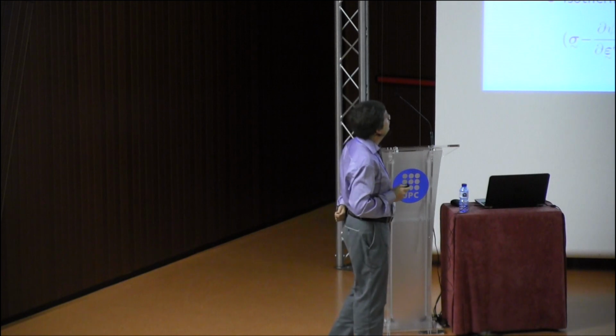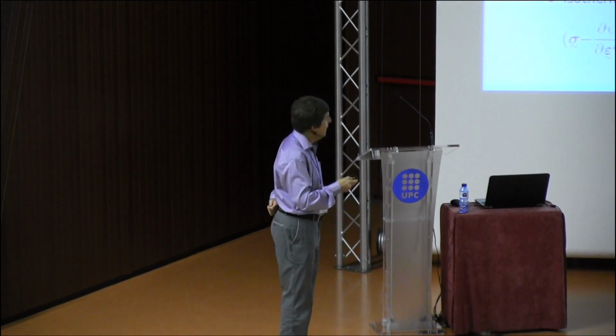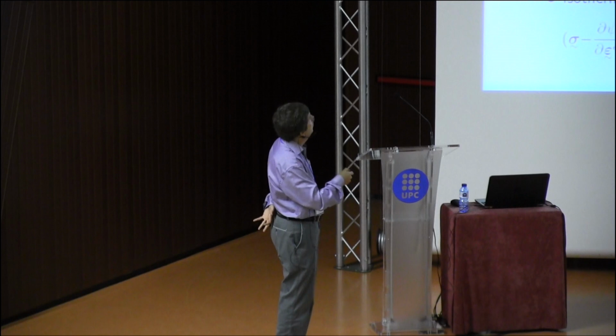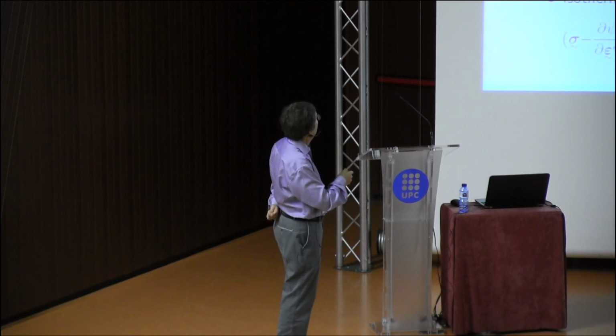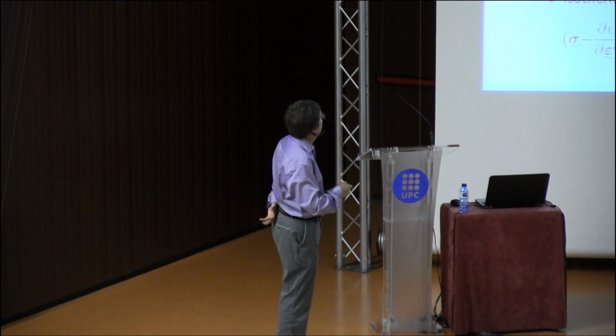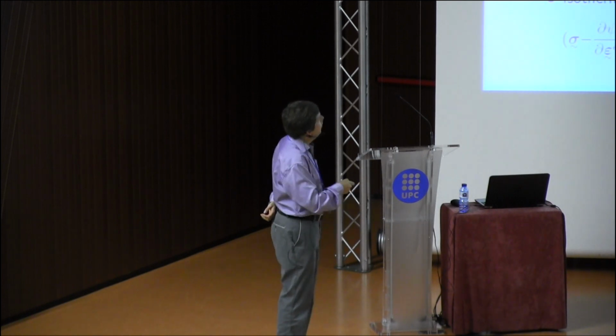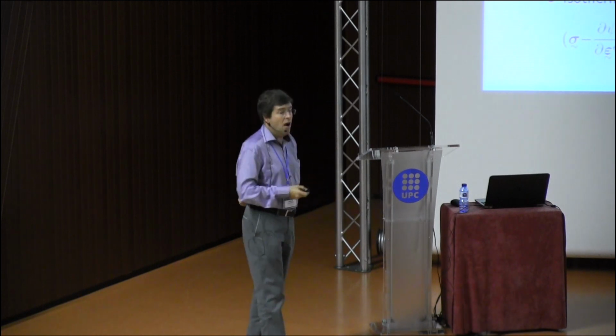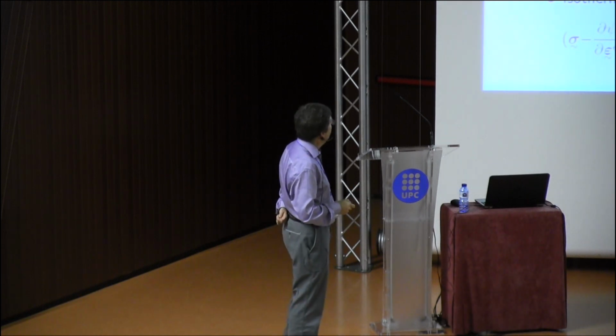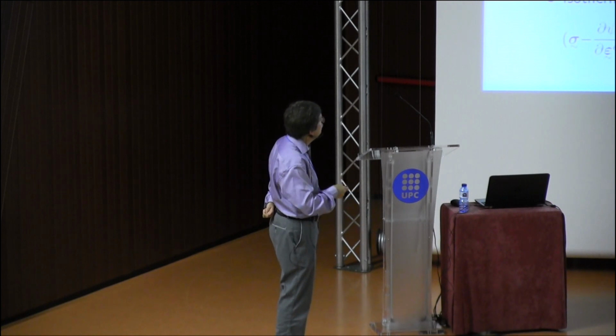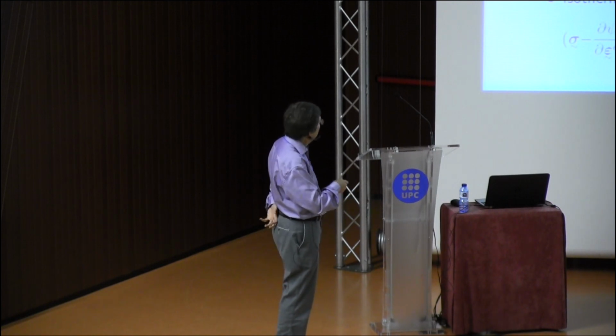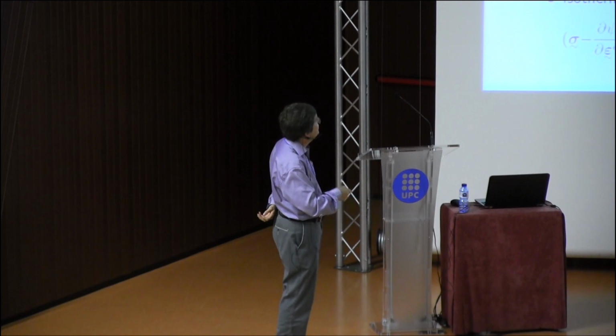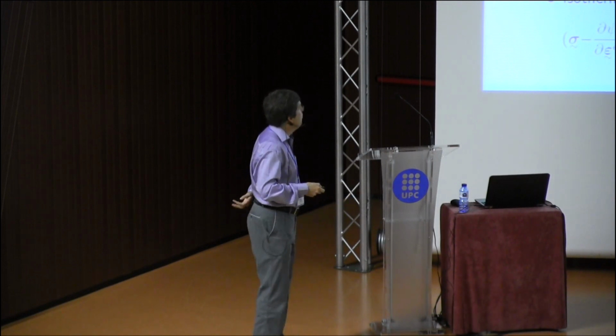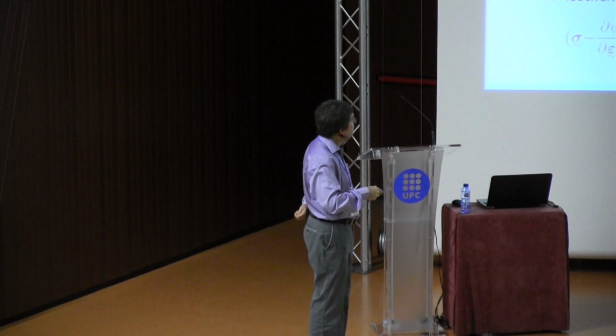Now we want to formulate the constitutive equations, and if you look at the formulation, there is no change compared to what you know with the internal energy density, the heat flux. I will discuss first plasticity, the split in elastic and plastic strain. Where are the changes? The changes are in red, in the constitutive functionals for the free energy function, the stress, the higher order stresses, and the entropy. If you plug this into the Clausius-Duhem inequality, you see this new contribution.